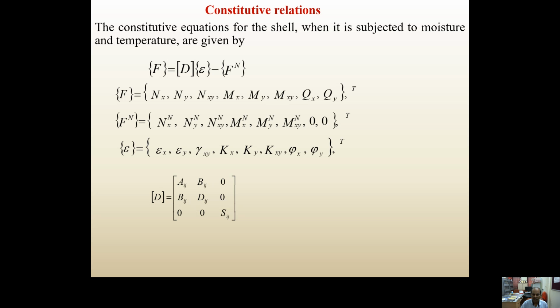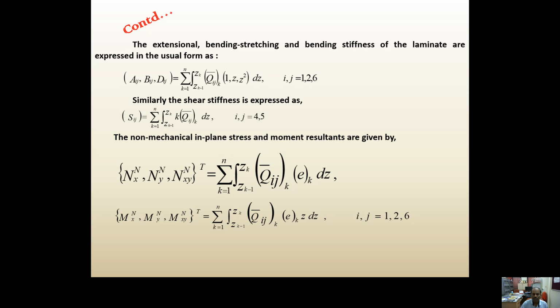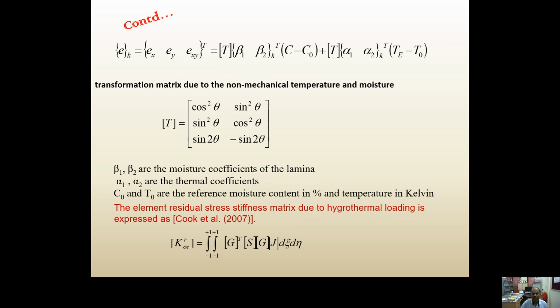So this is the constitutive relation D, which can be derived with respect to the stiffness coefficients. The in-plane coefficients, the bending coefficients, and the shear coefficients are found out like this. And a shear correction factor of 5/6 is considered throughout the analysis.